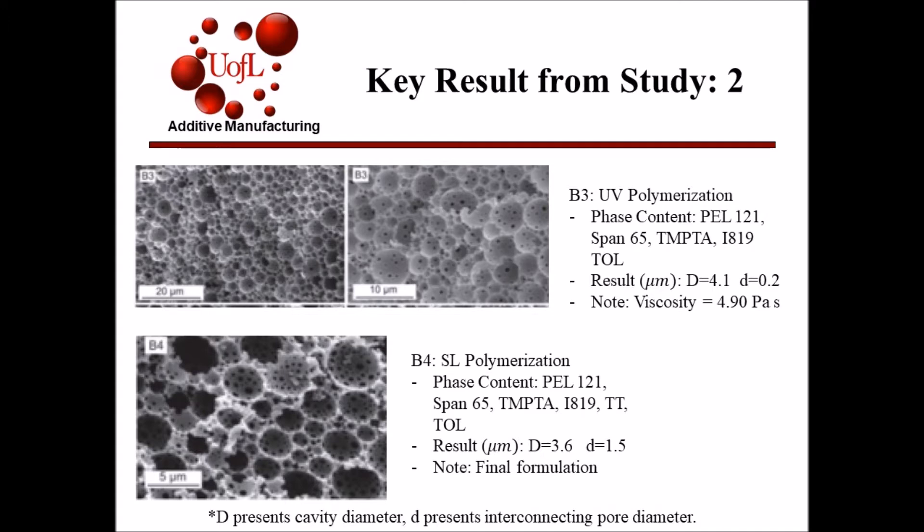The B4 formulation produced cavity diameters of 3.6 micrometers and interconnecting pore diameters of 1.5 micrometers.